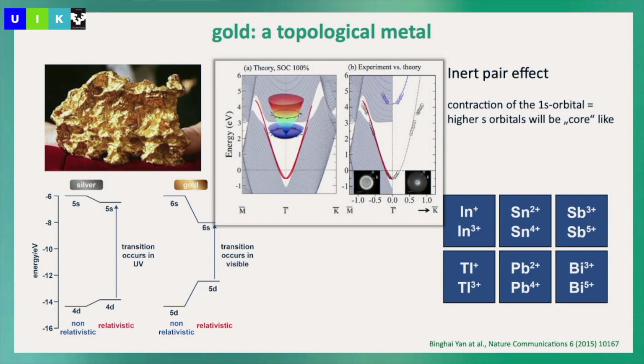Okay, so you can say it's not a gap, so we cannot take so much advantage, but the spin Hall effect, for example, or some other surface properties, even if the protection is not as nice as in the topological material, I'm still convinced that it has some impact on surface science. Okay, and as I said, this is why we love this kind of elements if you're thinking about topological materials, because they all have this inert pair effect, so the reduction of the 6s and 5s orbital to lower energy that leads then to this band crossing in the electronic structure.